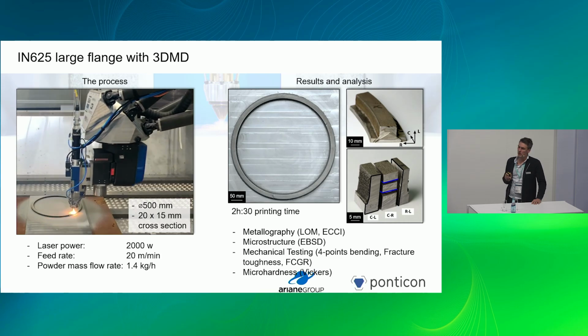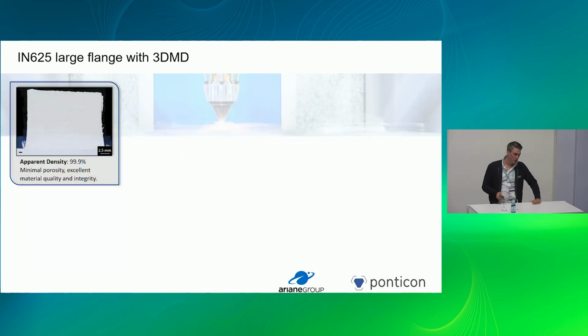And it's not only about processing time, but it's also about the features and the properties that you can achieve by influencing the microstructure. If you have a high feed rate, you also have very high solidification and cooling rates, which immediately affect the properties of what you deposit. And it's also important to keep in mind that in terms of microstructural evolution, this process is way closer to powder bed fusion than it is to actual DED, because we have those high feed rates and in turn high solidification and cooling rates.